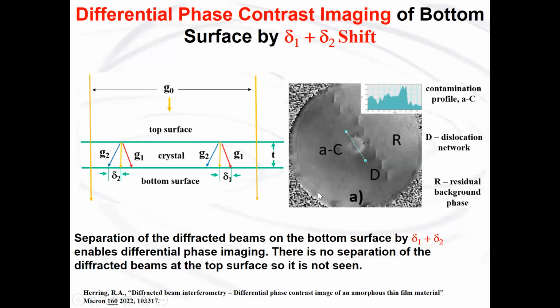The bottom of the crystal is imaged because the diffracted beams actually separate out their virtual sources, and now you can do differential phase contrast imaging. This isn't possible at the top surface, so we can't see that surface, but we can see the bottom surface nicely, and we can vary the separation by the thickness of the crystal that's being imaged. So on the right here is an example, and we can see there's an amorphous carbon spot on the bottom surface of the crystal and a dislocation network passing down here.